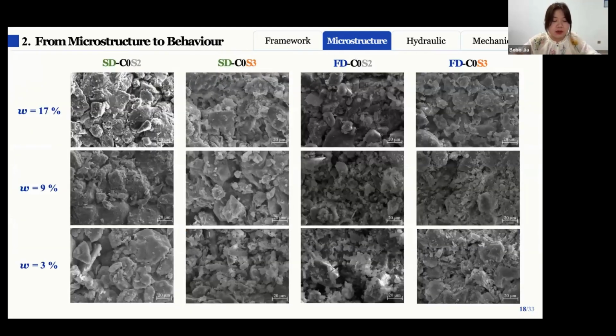Unlike sodium chloride, sodium sulfate tends to crystallize around its own nuclei, forming clusters of salt crystals that are unevenly distributed within the soils. The crystals also expand more during crystallization, which can cause more noticeable damage to the soil structure. If we look at the initial samples, we can see that the sample with higher sodium sulfate content, SDS3, appears more compact than SDS2. And under the faster drying condition, for the higher sodium sulfate content sample, the strong crystallization effect leads to the development of large suspended cracks between the soil particles.